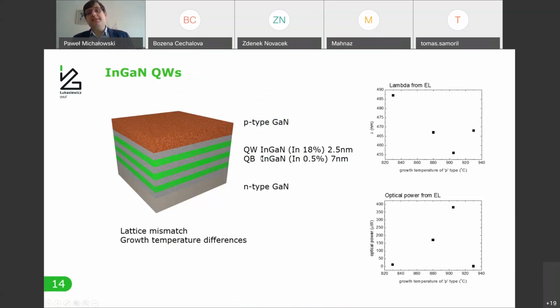Okay, staying with the nitride materials, I also made the analysis of indium gallium nitride quantum wells. The important challenge to make such a laser diode with such quantum wells is that the p-type material, which is grown on top of the sample, usually requires much higher growth temperature than the indium gallium nitride materials. And the other problem is that there is a huge lattice mismatch between gallium nitride and indium nitride.